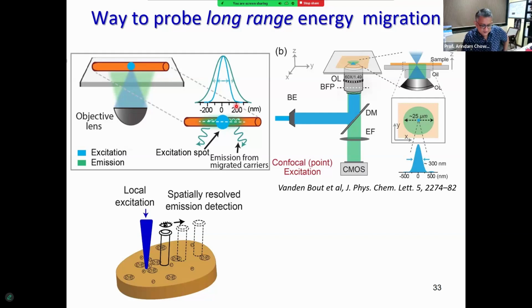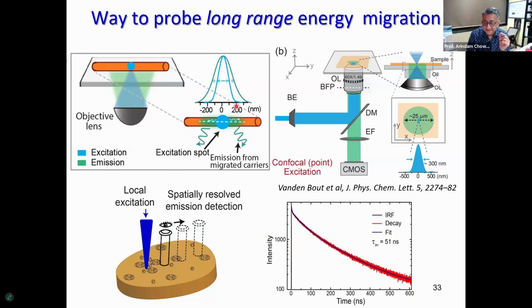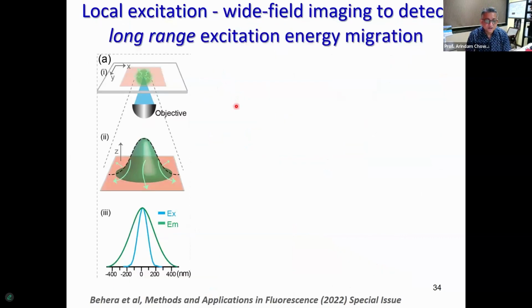So I call this, as in India we call it, a hack, or a cheap person's way of detecting the emission which is coming from beyond the excitation zone, provided the photoluminescence lifetime of the system is high. If the photoluminescence lifetime is very small, then the carriers would not be able to migrate and recombine. Before that, they would go back to the ground state, and luckily we found that it was quite high for these systems. So here's the experiment.